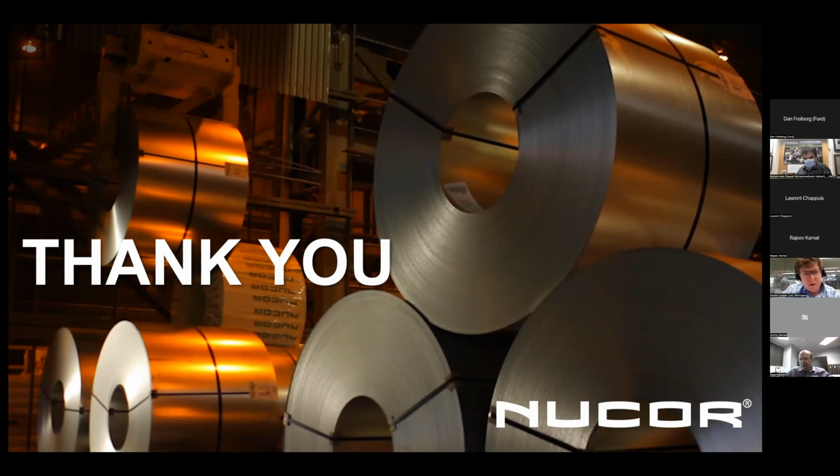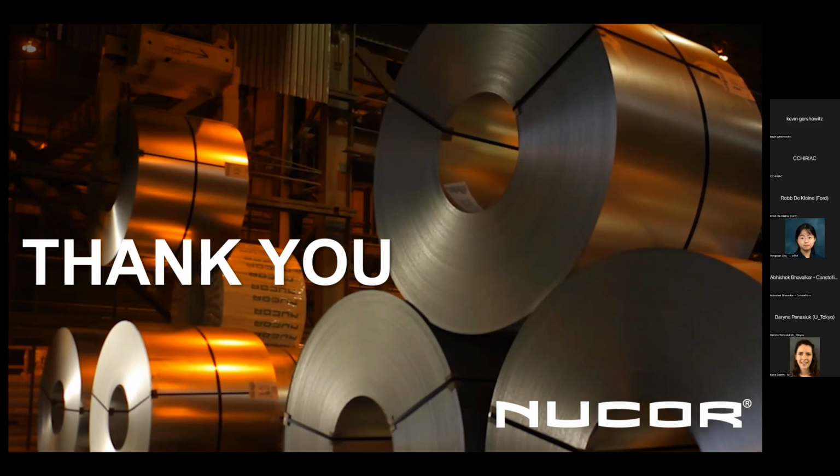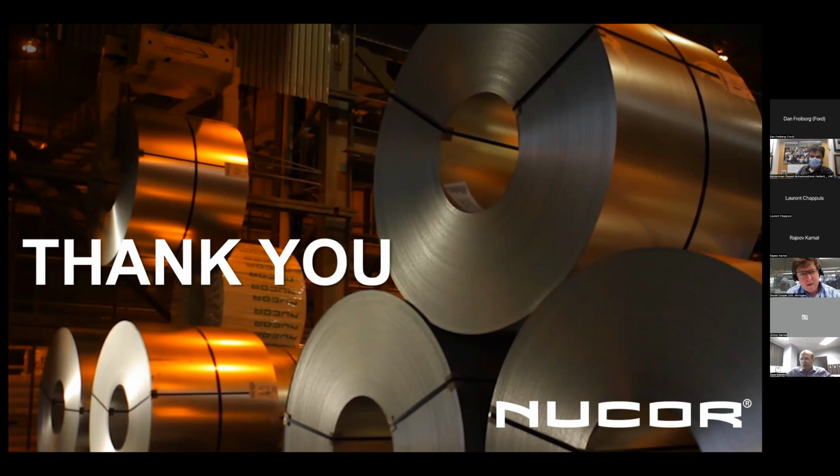So if they happen to be low copper requirements, typically a low copper is, we refer to it as less than 0.1 percent copper, then we call it a low copper scrap mix. Those are low residuals, low copper, and so we use a much higher scrap charge with more busheling and less shredded scrap to be able to make that.